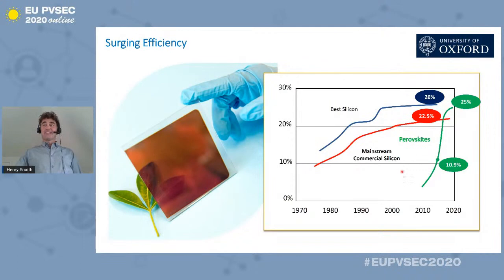lib. Anyway, the efficiency of the solar cells has increased tremendously, and even on our first publication, we reported 10.9% efficiency. This was right at the top of where the emerging PV technologies were at, and very rapidly the perovskite cells are approaching that of crystalline silicon. And in fact, there's nothing stopping them attaining the sort of efficiencies we see from gallium arsenide, even in single junction cells. But the question is, something new with only less than a decade of actual academic research and R&D, how can that compete with a technology that's got multiple decades of industrialization experience?